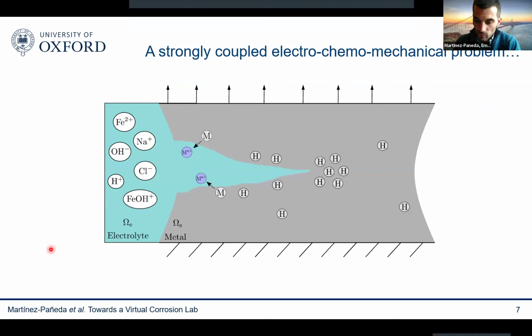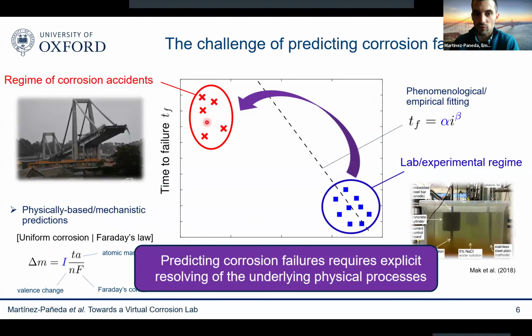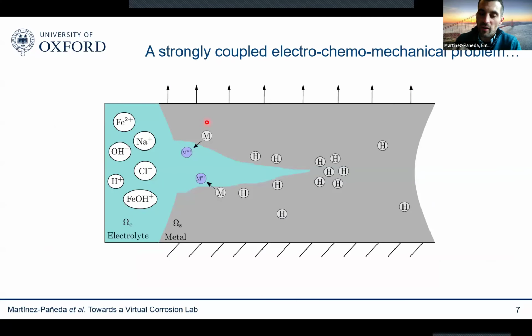The first one is that we finally have very powerful computational multiphysics tools. Why don't we have computer models for corrosion? Well, one reason, as I said, is that we do experiments in a very different regime than in practice. But the other aspect is that this is a very complicated coupled electrochemomechanical problem. This is a standard sketch showing a stress corrosion cracking problem where you have a metal that is subjected to mechanical straining. That metal has a defect, could be a crack, a pit. That metal is exposed to an aqueous electrolyte, imagine seawater. In that electrolyte, you have multiple ionic species moving around due to fluid flow, electromigration, and diffusion. Then at the interface between the metal and the seawater, you have multiple chemical reactions happening.